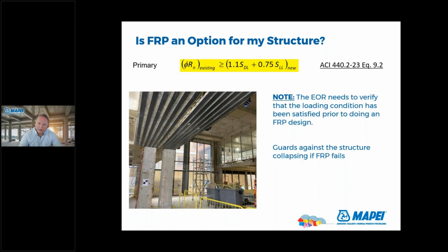And the reason for that is, if the structure cannot stand with the existing reinforcing in there, we don't want to add a bunch of FRP. Because what happens if there's a fire, or what happens if someone comes in and tries to vandalize the FRP and takes a grinder and cuts across these plates on this picture? We don't want the structure to collapse because of that. And so that's one of these equations that needs to be satisfied. So if it can meet the primary reinforcing, but you have additional loading, maybe additional safety loads that are going to be added, FRP is a great candidate.